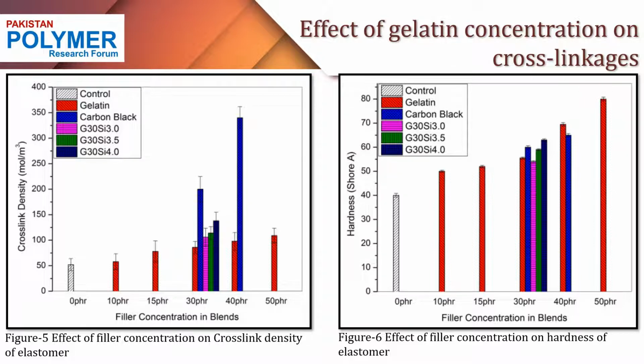The second graph represents the addition of filler with respect to the hardness of the blend. This graph again shows an increasing trend: with the increase in the concentration of gelatin, the hardness of the polymeric blend goes on increasing. Starting from 10 phr to 50 phr, the hardness goes from 50 to 80 Shore A. Along with this, you can also see that increasing concentration of silanized silica acting as a compatibilizer again increases the number of cross-linking points, making the material stiff and reducing elasticity, so it is harder as compared to the 0 phr elastomer that possesses 40 Shore hardness.